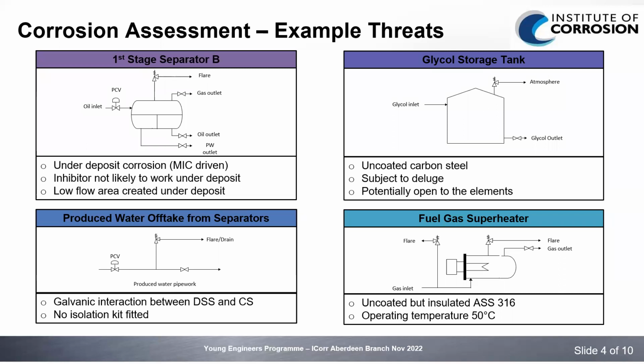first stage separator. The next one will be the glycol storage tank. It's not a hot storage tank, however, it is uncoated carbon steel and it's subject to deluge, I believe once every 12 months. And we don't have the plot plans of the platform either. So it could potentially be in a splash zone or just open to the elements in general. We've then got the produced water offtakes from the separators. These have been replaced with the duplex, as there was recorded CO2 corrosion, and also the nozzles were corroding due to sand erosion. But the one thing that they haven't accounted for is they've not removed the carbon steel valves, and there's also been no isolation kits noted to be fitted. So we'd like to fit some isolation kits just so that the carbon steel valves aren't quite at high risk.